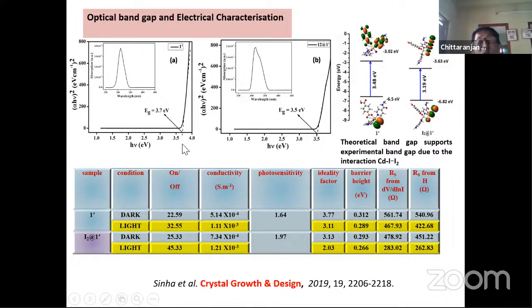You see, the molecule which is activated, this activated metal organic framework shows the conductivity at dark phase. It is around 5.14 × 10⁻⁴ Siemens per meter, while on light radiation, its conductivity is increased. And similarly, this iodine adsorbed polymer, its conductivity is slightly higher than that of the non-iodinated system. Thus, the role of iodine has also some importance in this regard. And the photosensitivity of the molecule is also enhanced upon absorbing iodine.